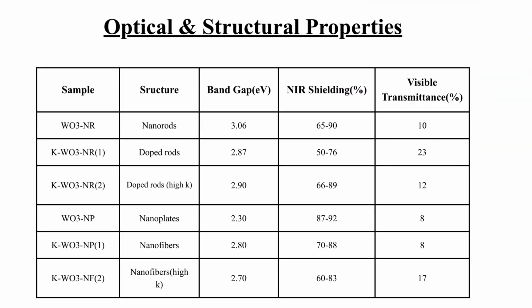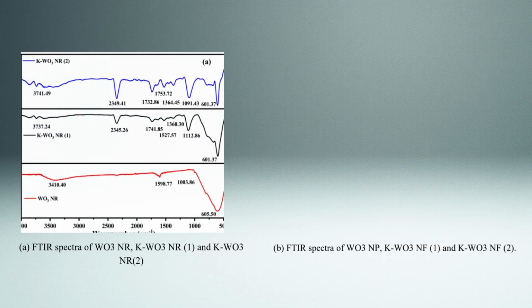Optical and structural properties. The table compares the nanostructures, showing that potassium doping effectively lowers the band gap, which improves NIR shielding in the nanorods, while nanoplates show the highest raw shielding. KWO3 samples, particularly the nanorods, achieve a crucial balance, which is strong heat blocking with acceptable visible light transmission, confirming their suitability for energy efficient smart windows.